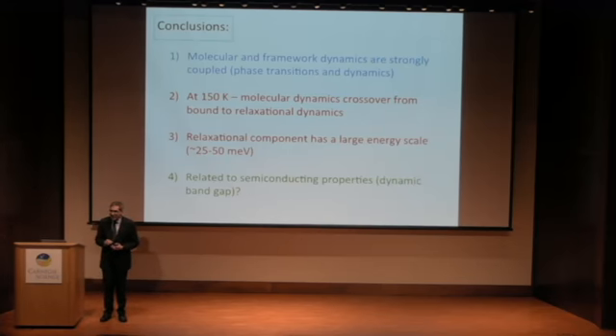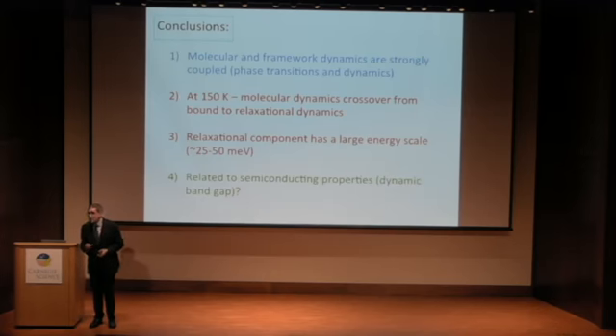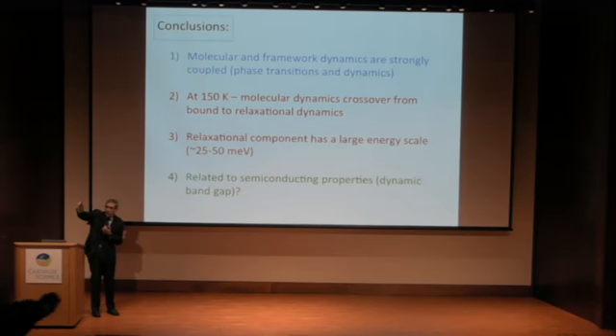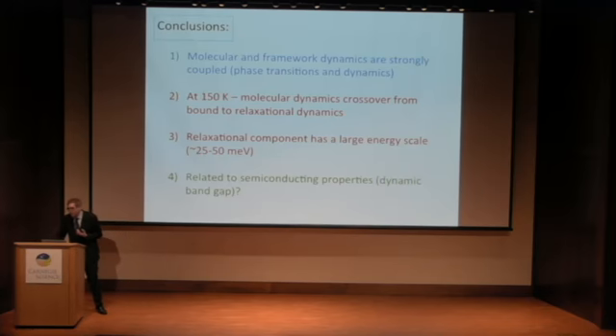Very quick clarifying question. When you're talking about rotations, are you talking about end-over-end rotations, or rotations around the axis of the molecule? So at low temperatures, what I think is happening is that you have your molecule, and it's basically doing this, so it's orientationally ordered. What I suspect is happening at high temperatures with this large energy scale is that it's basically doing that. It's basically gone free.